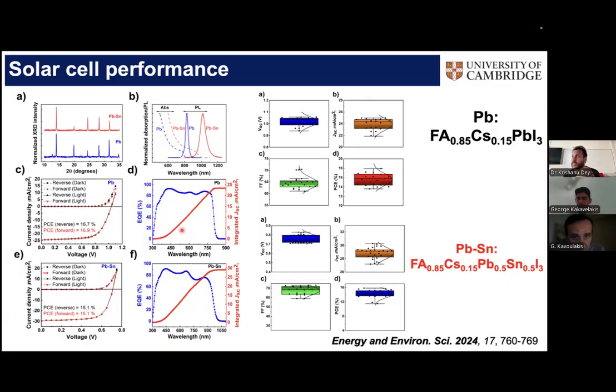So it's known in the literature that if you use any passivation in the bulk or the surface, they can have their own effect on ion migration. So I did not want to have any such combined behavior from the passivation and the tin. So I wanted to just specifically look at the tin, and hence I did not use any passivation. But of course, if you had some more passivation, maybe the process is even more suppressed. But then it's hard to distinguish what is and what is not due to tin.